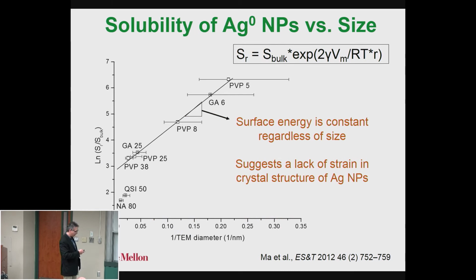Well, it turns out if you actually look at the solubility relative to the bulk as a function of size, and going this direction, things are getting smaller, because it's 1 over the diameter. So these are my smallest particles. You get this line. They do get more soluble as they get smaller.